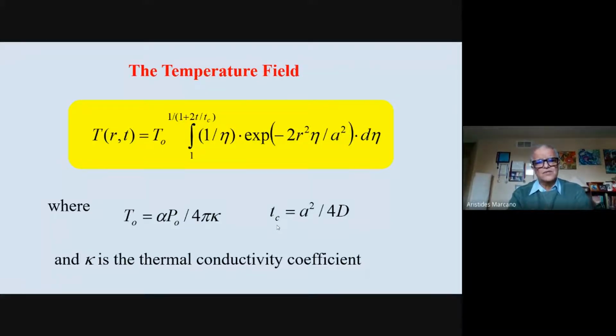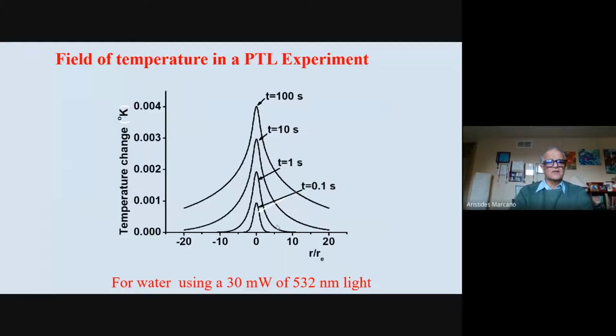Anyway, that's a very well-known equation that can be solved easily, despite this impressive view. But anyway, that's the solution. I calculated it myself using MathCAD. And you can see at the beginning, I put that at the time 0.1 seconds, so it's 100 milliseconds. So you have a distribution of temperature that follows the Gaussian beam. It's around the radius of the Gaussian beam given by this r_e. So it's just some kind of thermal photograph of your Gaussian beam. But over the time, there is some diffusion, the diffusivity is acting, and then that starts spreading. And also because you are pumping all the time, that will grow in amplitude.